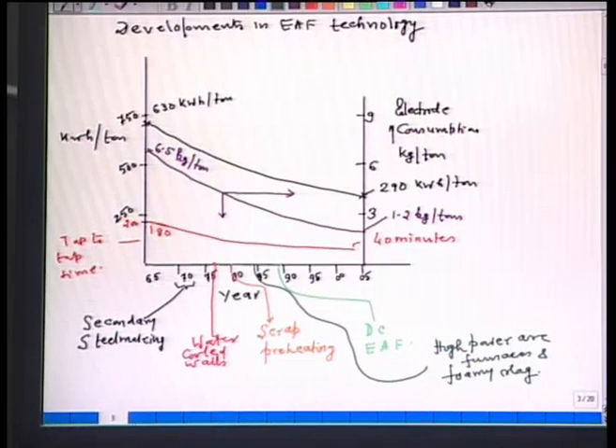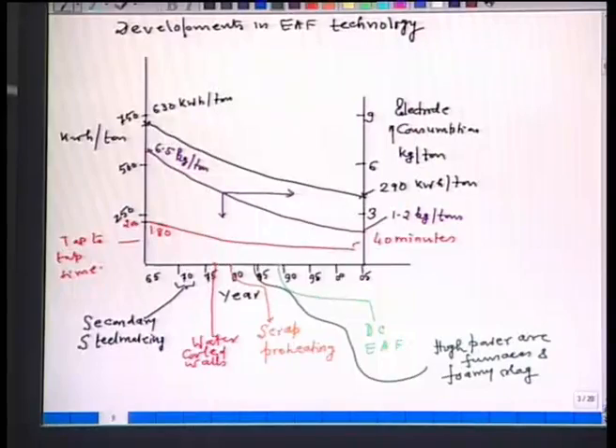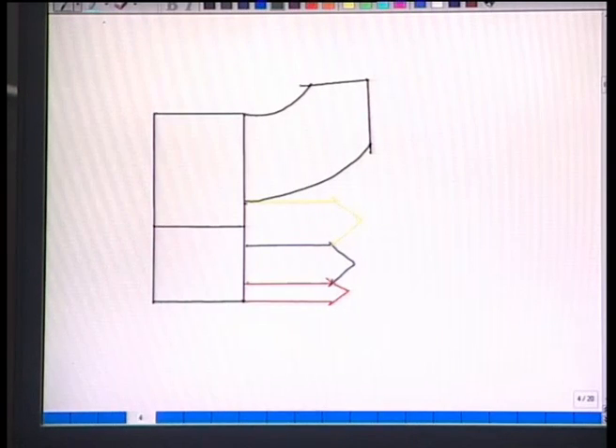For your information, these years which I have shown, they are approximate, they can vary by a year here and there, but what I wanted to emphasize is the fact that continuous development in the electric arc furnace technology made it possible to decrease the power consumption, to decrease the electrode consumption and to decrease the tap to tap time, with the result refractory consumption will also decrease, because now the electric arc furnace vessel is handling liquid steel for a small amount of time.